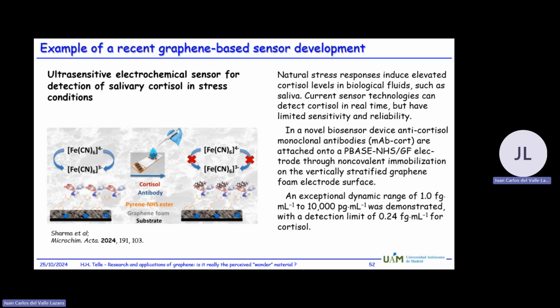And there's a description how to do all that. You prepare your sample with sensitive acceptors, and then you can detect these compounds here. And the huge advantage of these sensors evidently is that they're small, which is one. They're also flexible, because graphene is only a monolayer, so you can attach it to your skin, for example. And they have tremendous dynamic range, so you can go from femtograms in a milliliter to something like picograms in the milliliter. And this is something which is superior to many other sensors, which are accurate in a small range, but not over such a wide range.